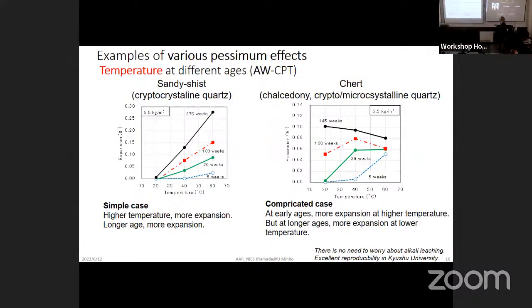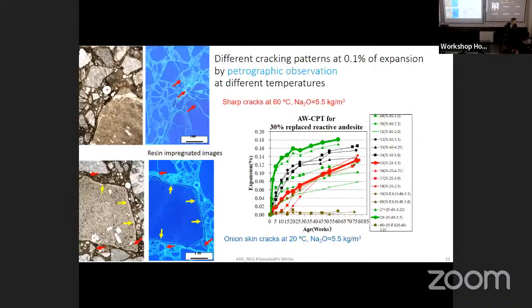But in another case, this is the case of gel containing chalcedony and microcrystalline quartz. At 5 weeks, higher temperature shows a higher expansion. But at longer age, lower temperature shows more expansion. This is quite strange. This is another case.